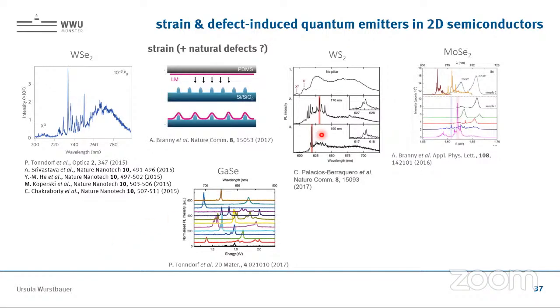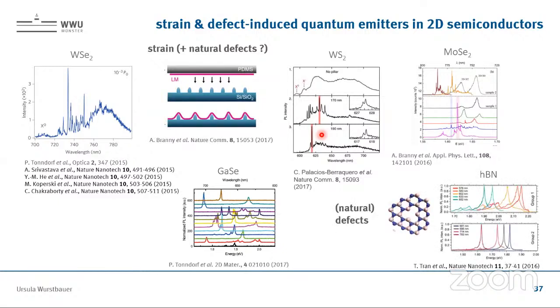However, the energy cannot be well controlled. So that's a little bit of an issue, but you know, that's engineering. So we are working towards that direction to become better here. There's another material which is also promising, hexagonal boron nitride. The natural defects can also serve as quantum emitters, still at different energies. However, the advantage here is that it's at room temperature. All those others are at low temperatures, at cryogenic temperatures.